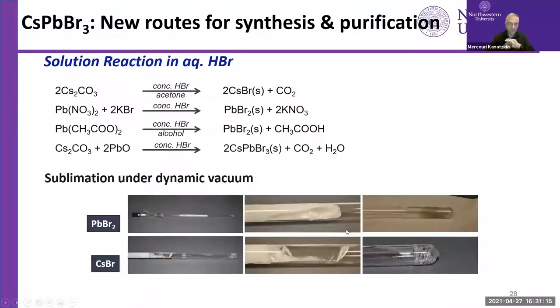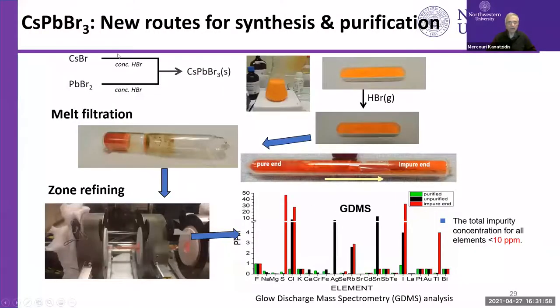So then we went back to the lab and started purifying the compound. We can make, for example, high quality cesium bromide and lead bromide, starting from say cesium carbonate or lead nitrate or lead acetate, and we use very pure hydrobromic acid, and we can precipitate these materials. Then we filter them, and then we put them inside a tube and heat them up so that we can evaporate them from one side to another and leave behind the impurities. We sublime it and get very high quality material. Then we use that to combine them and do the reaction to give us the cesium lead bromide that you see here.